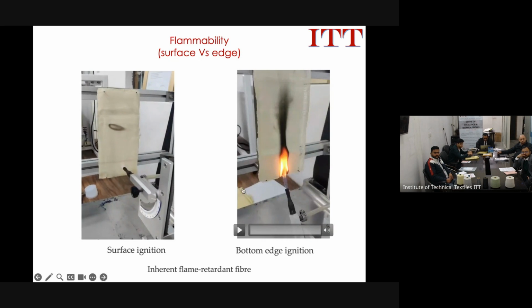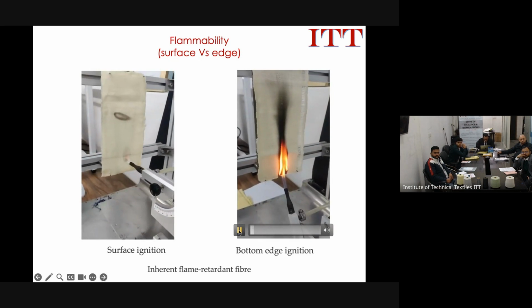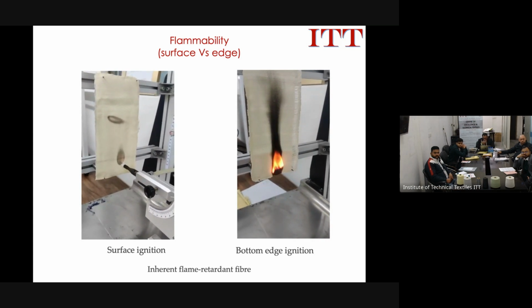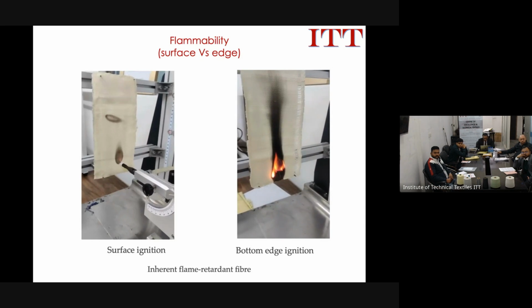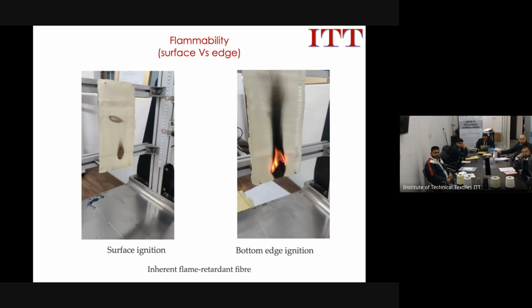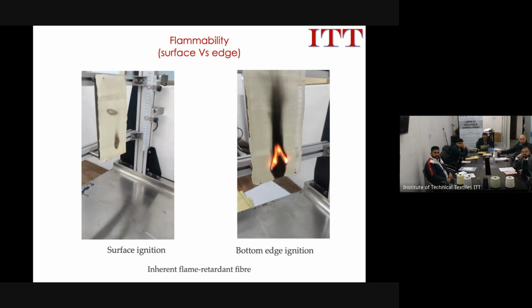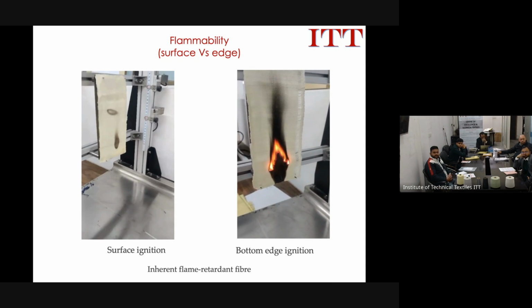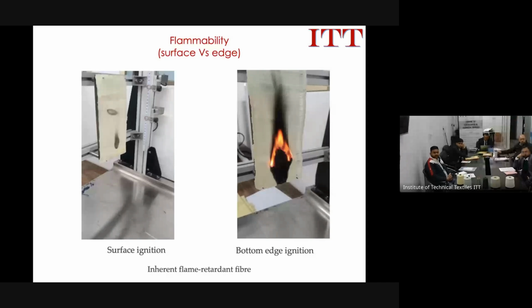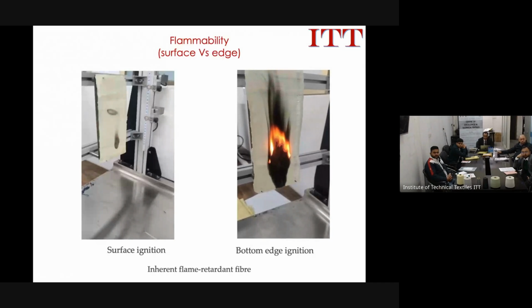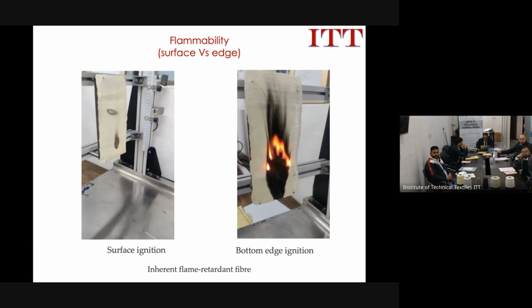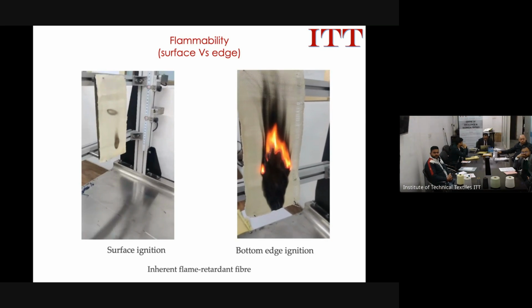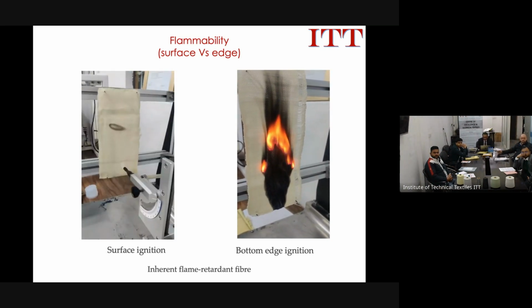In this example, we performed a basic flammability test and we found some surprising results. Again, we are cross-checking, we have ordered new lots, and we are trying to understand why it's happening, why it's giving very good results in surface ignition, and slightly doubtful results in bottom ignition. So all I'm saying is that we should do our own testing with the material. It doesn't matter where it's coming from, it doesn't matter who is manufacturing, but we should do our own validation, because sometimes there's a problem in a certain lot, which can be a problem for you because these are very costly fibers.